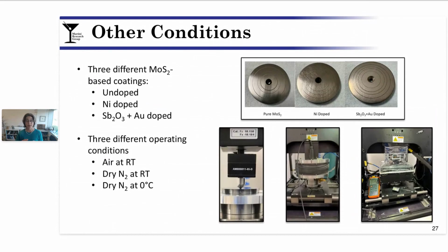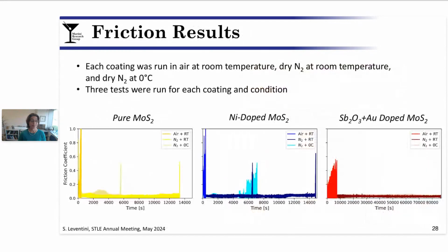Next, we extended this study to include another dopant, in this case, an antimony oxide gold, which is a little bit more of the state of the art these days for MoS2 dopants. And we also explored other conditions. So we moved on from air at room temperature to dry nitrogen at room temperature to dry nitrogen at 0 degrees Celsius.